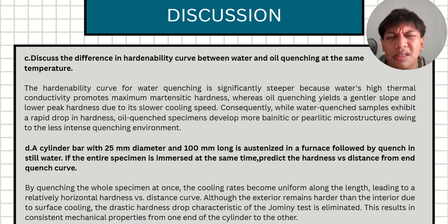If a specimen is fully immersed in water all at once, the cooling rate becomes uniform along its entire length. This eliminates the drastic hardness drop seen in a Jominy test, resulting in a horizontal hardness curve with consistent properties from one end to the other.